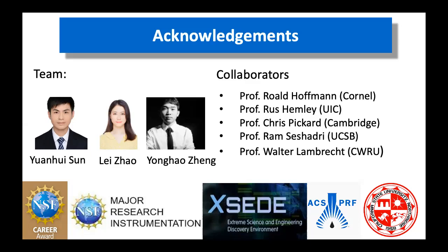But that's okay. Another thing, just to add one more fact about the BCC. Following your suggestion not to look down on the BCC, I just learned from Chris Pickard that if you take a uniform electron background, a uniform charge background, with positive point charges, and you just calculate the Madelung energy, then the BCC actually is the most stable one. So that's another story. But with this story, with the subset matching and subset mismatching and repulsion, you can explain that BCC becomes stable, and eventually also that it becomes non-stable. So I think it does reveal something really hidden there. It's the driving force.